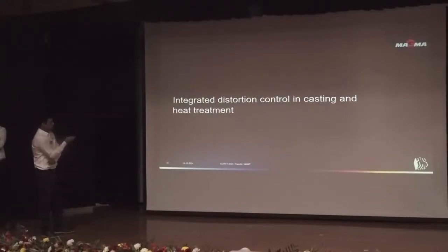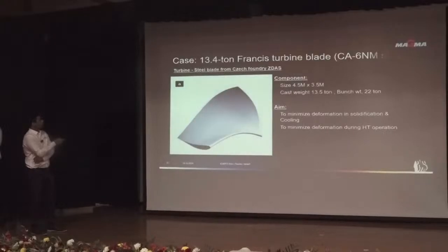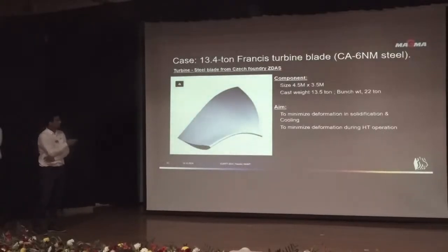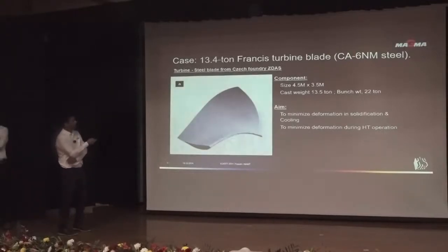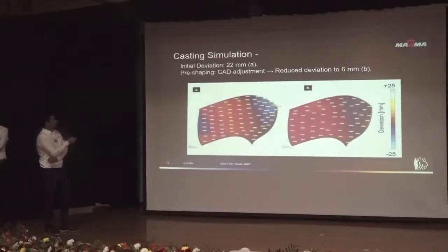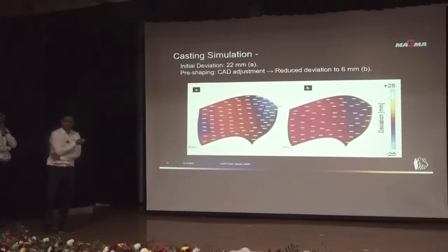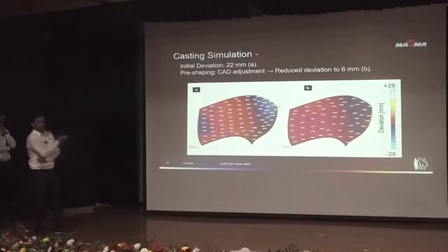There is also one more thing, which is integrated distortion control in casting during heat treatment. This component is a very big turbine blade, with a size of 4.5 by 3.5. Our aim was to minimize the deformation during solidification and cooling, and also during heat treatment. The initial maximum deviation was 22 mm. The images are a little blurred, but you can see by the color. By pre-shaping with CAD adjustments based on the simulation results, we reduced the deviation to 6 mm.